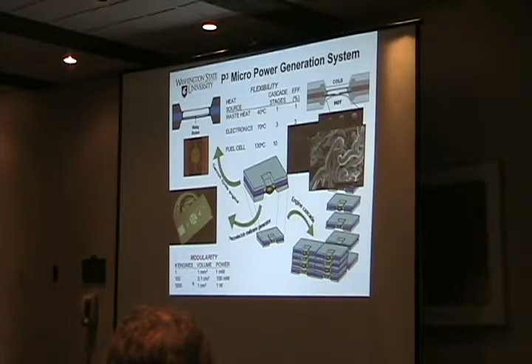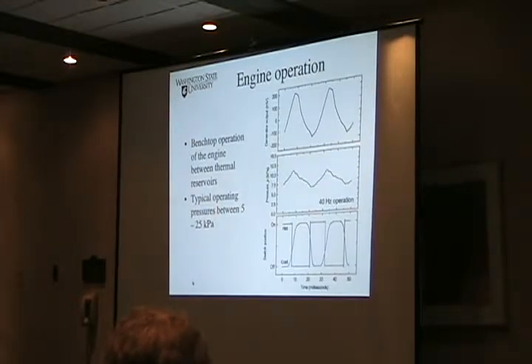But the idea is that we have a modular system where if we heat up this fluid and we can pass the waste heat from one into the next layer on top of it, we have a little set of engines that we can lay out in sheets or stacks, take advantage of different low-grade heat, and hopefully be able to hit efficiencies on the order of 1 to about 8% of Carnot efficiency.